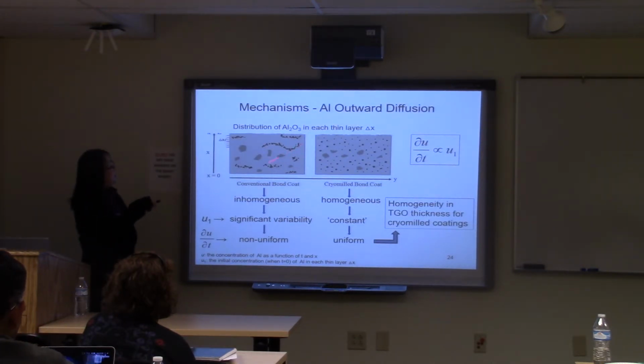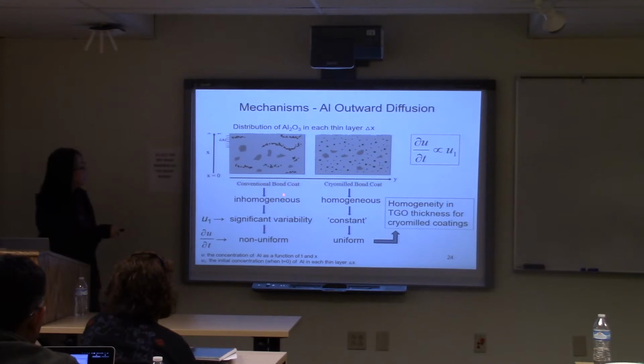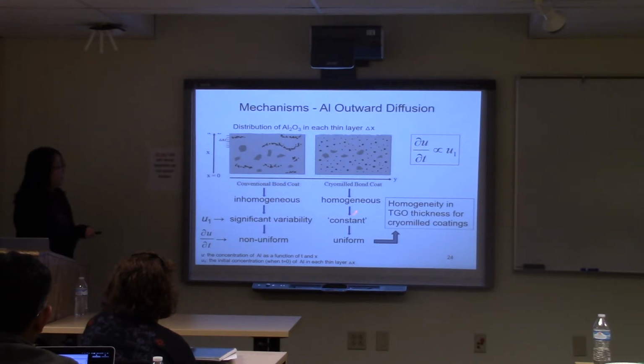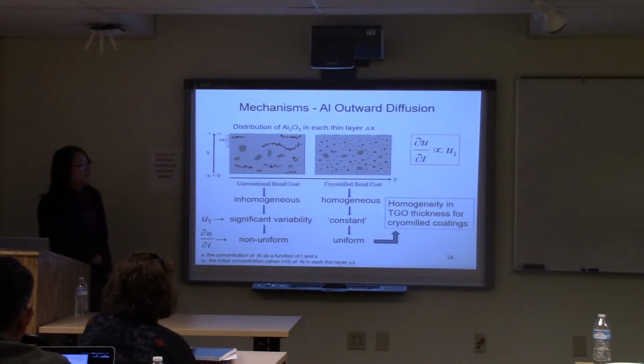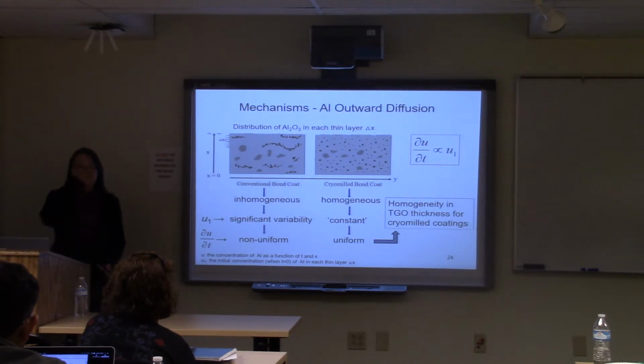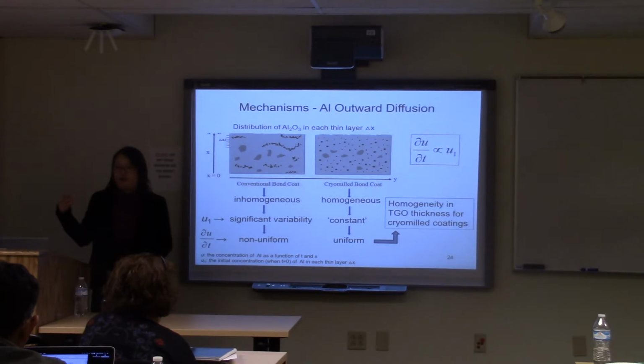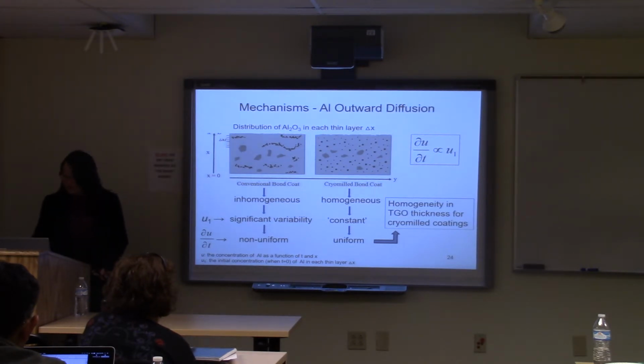So the mechanism that comes out is that the aluminum outward diffusion is controlled by this homogeneous distribution of the aluminum-rich oxide, which gives you a more constant aluminum concentration profile at each divided thickness here. And it finally gives you the uniform and homogeneous TGO thickness of the cryomilled coatings here. And because of the more homogeneous rate of aluminum diffusion, you can avoid all those spinel, the second phase oxides here.